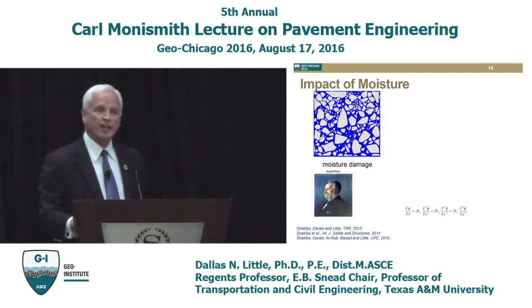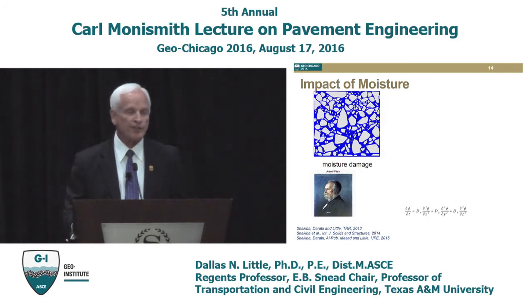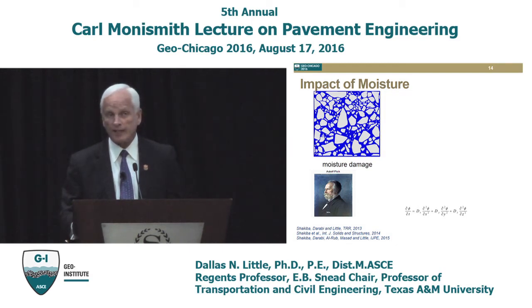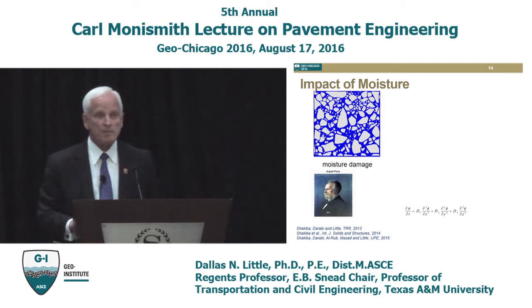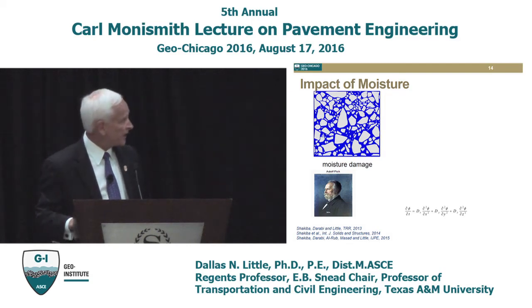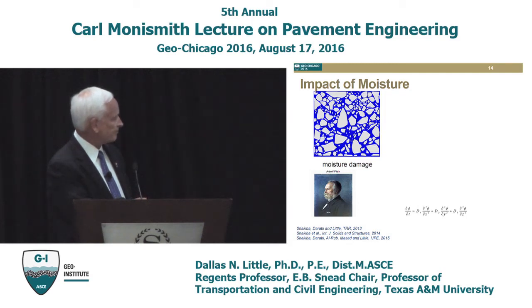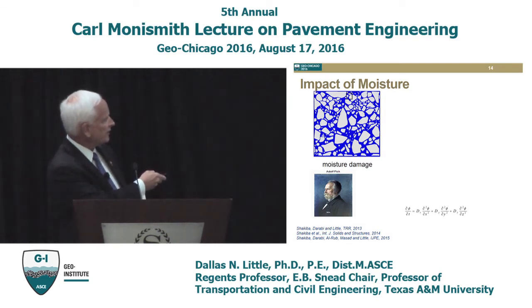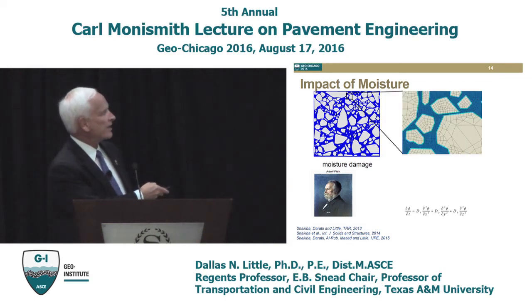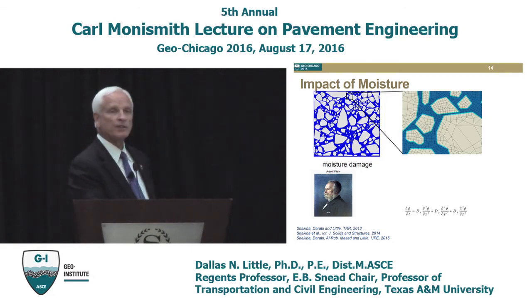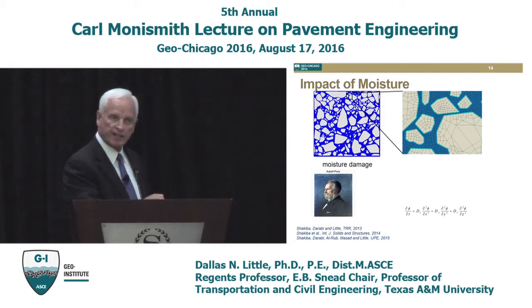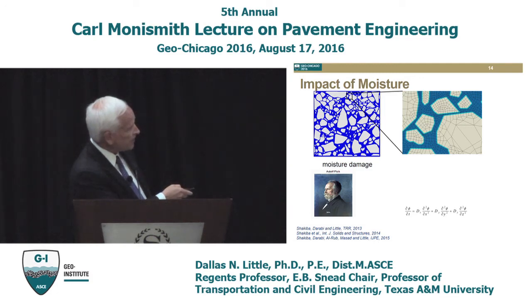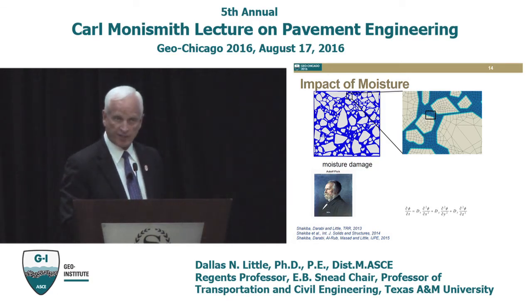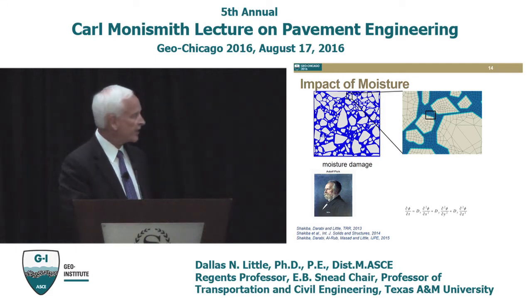We would get that structure of the asphalt from some type of imaging technique such as tomography. We would understand what the shape of the aggregate particles look like. And the blue in between the aggregate particles would be the mastic, the fine aggregate matrix. So in this particular micromechanical analysis, we're going to look at a component right up here of the mixture, and we're going to blow that component up. The aggregate is considered to be elastic. The blue material within the aggregate would be the fine aggregate, the asphalt in the fine aggregate, mineral filler and so forth. And you can't see it on this particular slide, but you've got a little light blue interface, which is the adhesive interface. So we can characterize the nature of that adhesive interface as well.